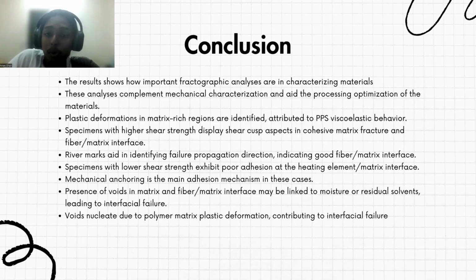In conclusion, the results show how important fractographic analyses are in characterizing materials. These analyses complement mechanical characterization and aid the processing optimization of the materials. Plastic deformation in matrix-rich regions is identified, attributed to PPS viscoelastic behavior. Specimens with higher shear strength display shear cusp aspects in cohesive matrix fracture and the fiber matrix interface. River marks aid in identifying failure propagation direction, indicating a good fiber matrix interface. Specimens with lower shear strength exhibit poor adhesion at the heating element matrix interface. Mechanical anchoring is the main adhesion mechanism in these cases. The presence of voids in the matrix and fiber/matrix interface may be linked to moisture or residual solvents, leading to interfacial failure. Voids nucleate due to polymer matrix plastic deformation, contributing to interfacial failure.